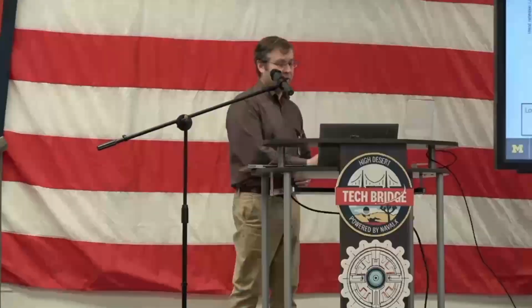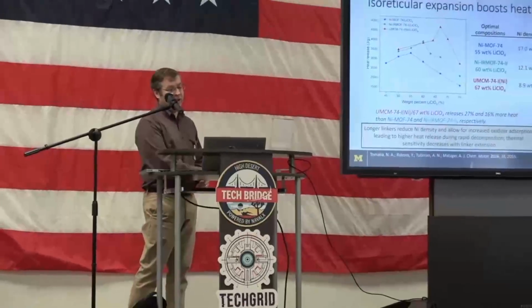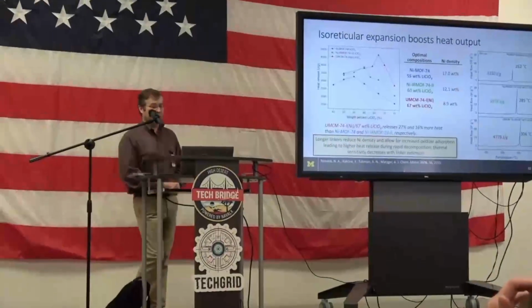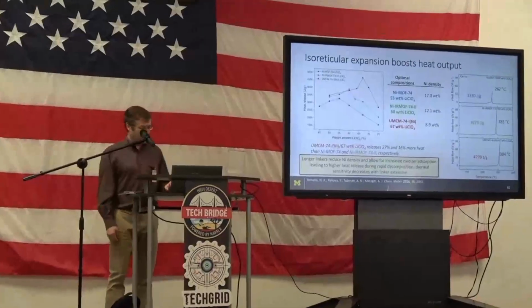So we made this linker 3 nanometer pores, and now we are finding that we should be able to load up to make even positive oxygen balances in this case. And so we then do that whole series of measurements, and we find indeed we can get up to 67 weight percent of lithium perchlorate is giving us our maximum heat release, and that heat release is substantially higher than these other metal organic frameworks, so this is starting to be actually pretty good.